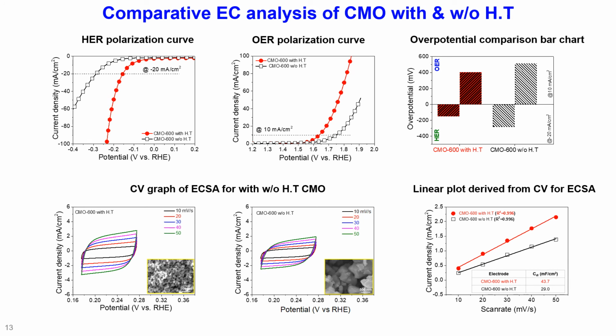Comparative ECSA analysis of CMO without the HT has been shown here. Here we could obviously see that the CMO 600 synthesized from the HT treatment shows very better activity of HER and OER. And also the particle size difference is very clear from this CV graph. The inserted image shows the SEM image of those two nanoparticles. Here we could clearly see that the particle size is very different and morphology is also different. So the particle size and morphology influence much the electrocatalytic activity towards water splitting.